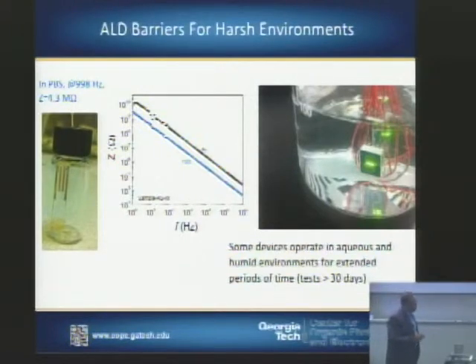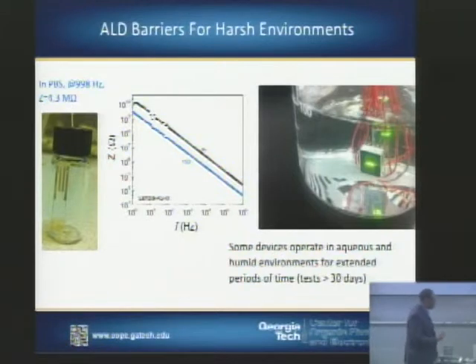Interacting with the group at Utah, we have some capacitive devices that we place our ALD coatings on top of, and this shows the impedance spectrum as a function of frequency, showing the quality of the coating. Some of these devices have been operating for more than 30 days in saline solution, also showing very low leakage current. So again, we're looking at not only the creation of ultra barriers, but barriers that could withstand very harsh environments.